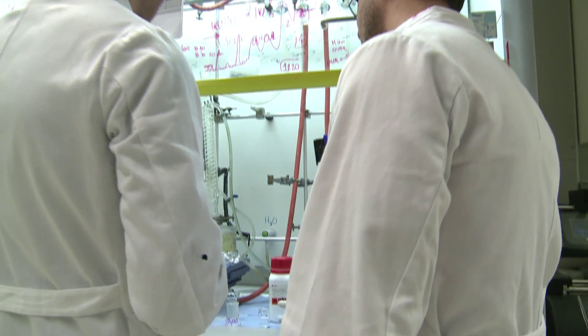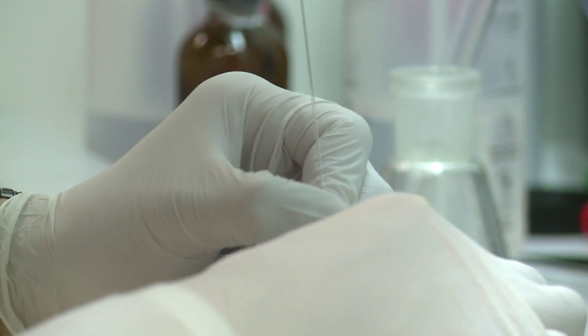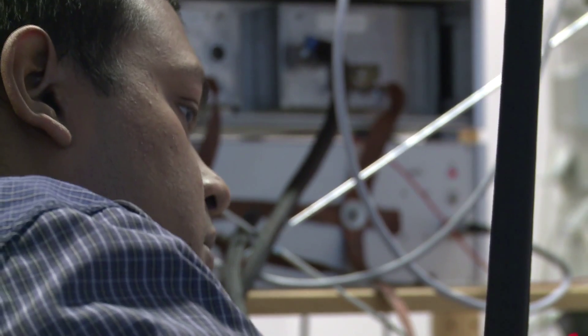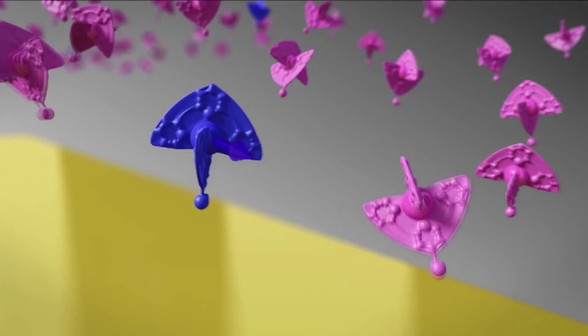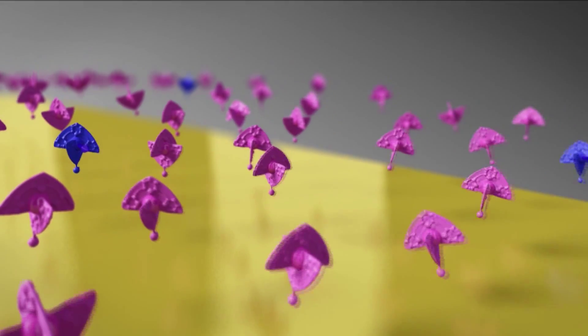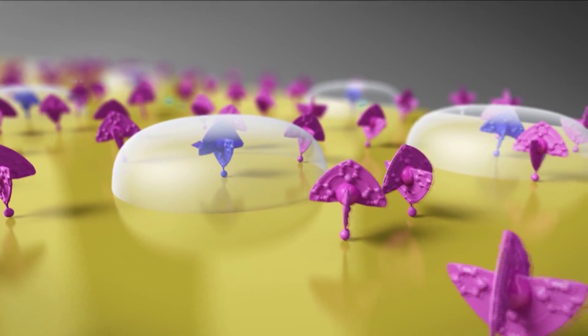A lot of the work done there is incorporated into our devices. The collaboration with Wilfred van der Wiel aims at locally doping electronic structures via molecules. We design molecules with particular dopant atoms, synthesize them in our lab, and put them on the surfaces he wants. In his lab, they do the structuring of electrodes and study the electronic properties. You can design molecules with a magnetic atom, and by coating the surface with a thin metal layer, you can tune the spintronic properties of the metal layer through the magnetic atom embedded in the electrode.